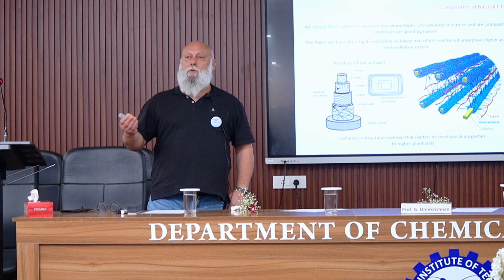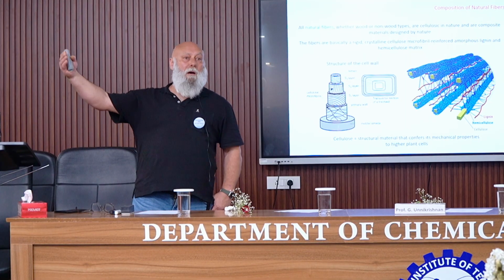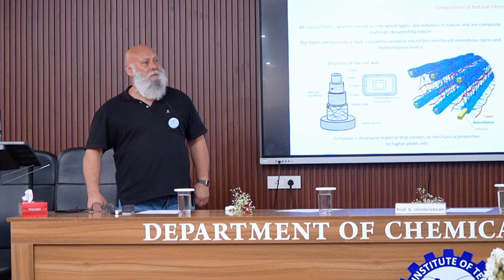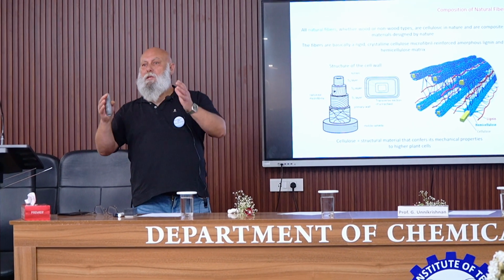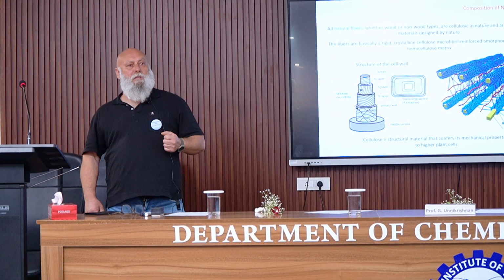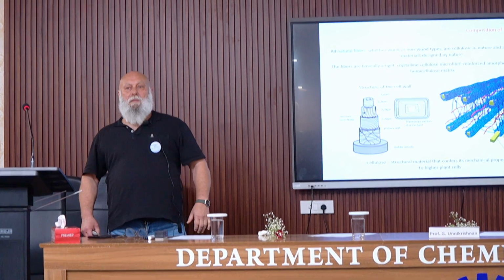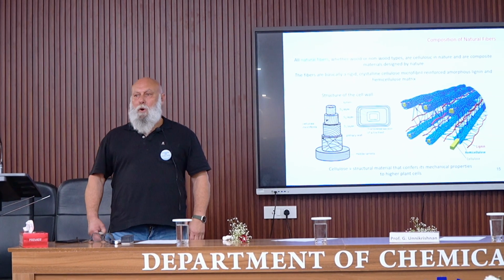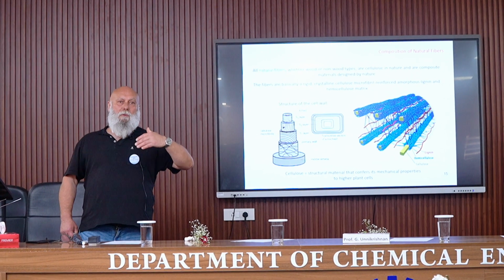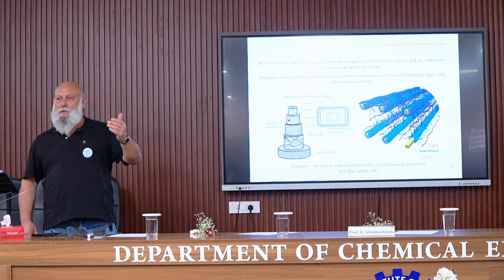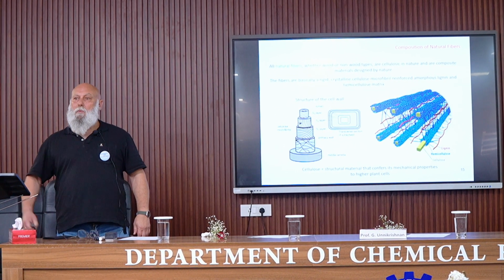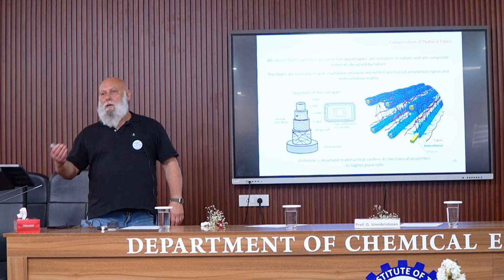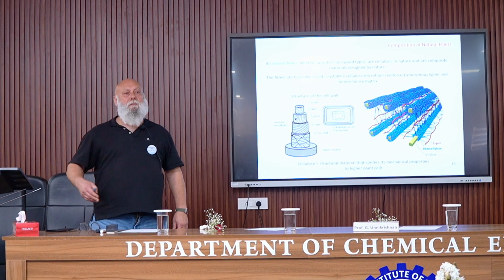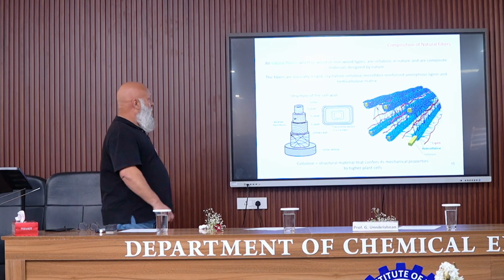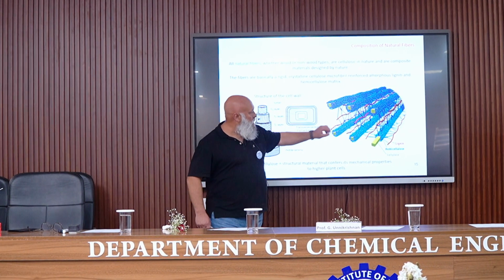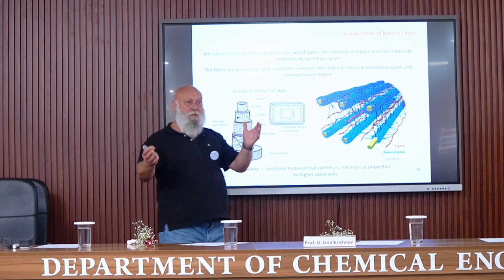You know that cellulose is hydrophilic, and usually the plants are outside, of course. So it's necessary to protect the cellulosic material from moisture. And for this, there is a matrix which is composed of another polymer, called lignin, which is a hydrophobic polymer that protects cellulose fibers from moisture. And of course, because we are considering a hydrophilic and a hydrophobic material, it's necessary to compatibilize these materials. This is the role of another component, which is called hemicellulose. And we can find also some other materials like waxes, pectin, and so on. But these are the three main components of natural fibers, which are represented here: cellulose, coupled with hemicellulose, and the matrix is lignin.